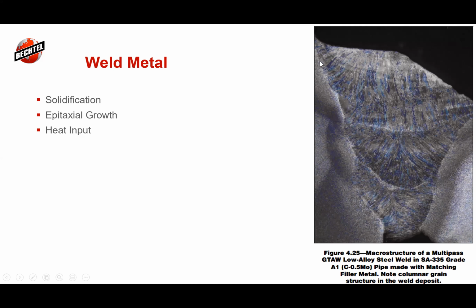And our welds will solidify from the sidewalls, where the heat affected zone is, and we can see the nice heat affected zone here delineated by the halo in color. But the weld metal comes off that fusion line, and the direction as it comes off is called epitaxial growth. That means that the liquid starts to solidify, almost like when you put ice cubes in your freezer. You can see the same directional growth, unless you have a really special freezer and make those really nice spherical ice cubes that they put in bourbon or whiskey. Those, you try to get it out so it's clear. But your weld will solidify coming inward.